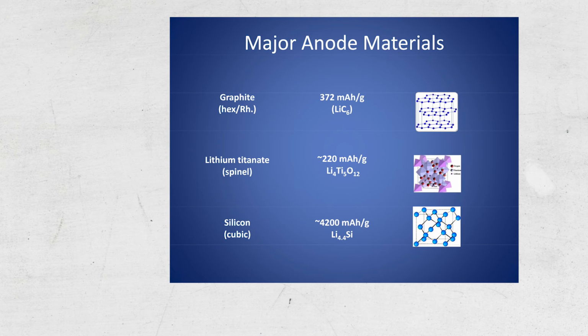It's very highly reversible, because when you put lithium into the graphite, the carbon-carbon bond, which is very, very strong, never breaks. This binding energy between carbon atoms is stronger than in diamond. Stronger than in diamond, so it's almost unbreakable.